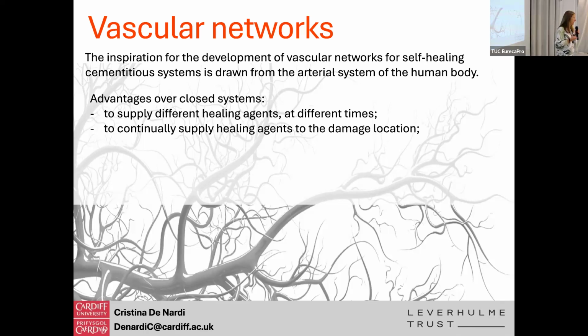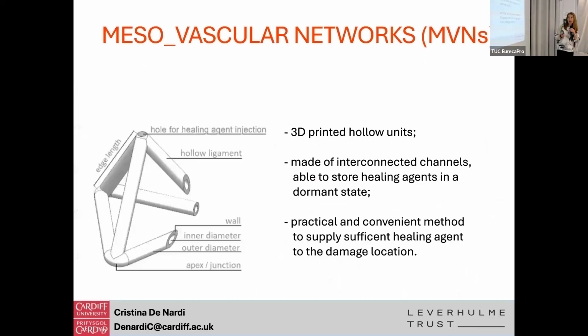But as you can imagine, the real scale is not yet constructed. So in Cardiff, we have developed an alternative technologies, which is still keeping the concept, but is quite more reliable. And we designed what we call mesovascular networks. They are, again, 3D printed hollow units. They are made by interconnected channels. They can store healing agent inside. So when you have a crack, and the crack crosses one or more of those ligaments, then they are broken, and at that time they can release what was stored inside.